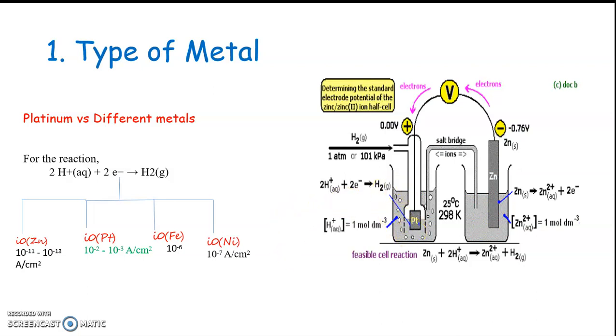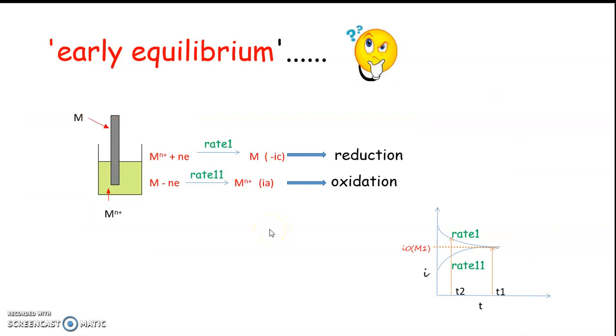For this reaction, the exchange current density of platinum is shown to be 10 raised to minus 2 to 10 raised to minus 3 ampere per centimeter square, which is very high compared to the exchange current density on a zinc surface, which is in the range of 10 raised to minus 11, and iron or nickel for the particular cathode process. That is, platinum acquires an early equilibrium and produces a higher exchange current density. How does it establish an early equilibrium? When a metal is dipped into its solution,